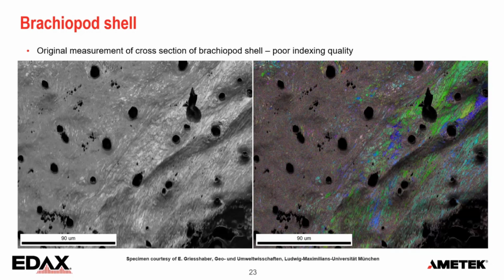So when we collect a map here, on the left, the top left, we have an area that indexes almost nothing in the IQ map. There's no contrast. Those black circles are organic conduits. So there's organic material going through the structure. And here on the lower right, that's the outer edge of the shell. There we have better crystallinity, and we have better patterns. We can see that here on the right. We also have nice indexing, but still a lot of noise pixels in between, where the pattern quality was just not good enough to index.